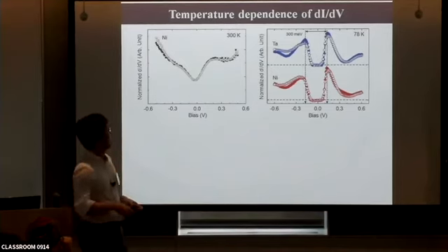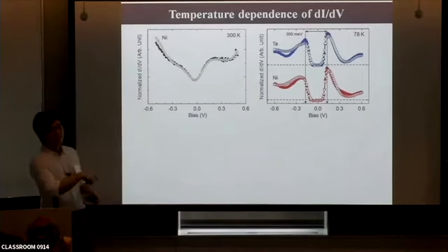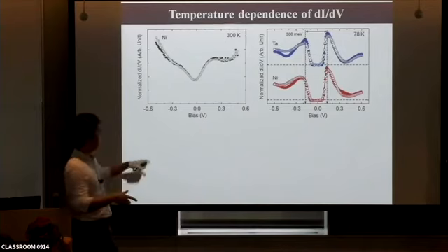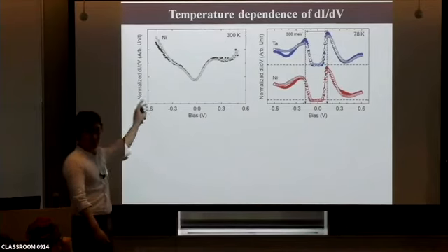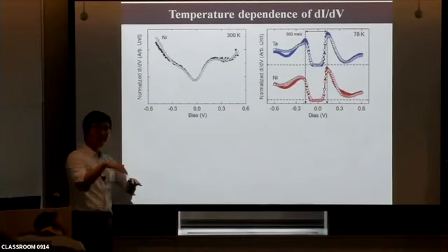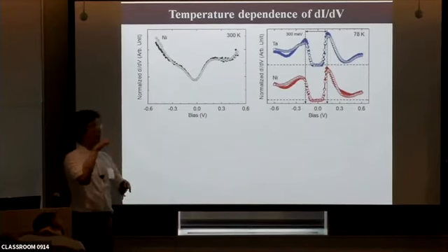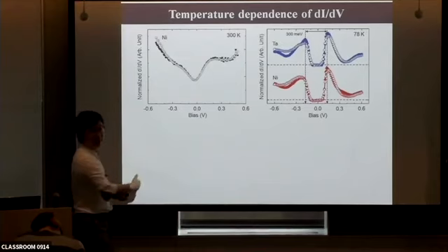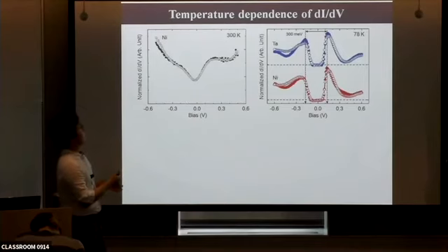I mean, it's definition. But in this study, I'd like to argue that the STS measurement observed the band character inversion, and this band character inversion is only explained when we consider the normal phase as the semi-metallic band. So this is another evidence of the semi-metallic high temperature phase.